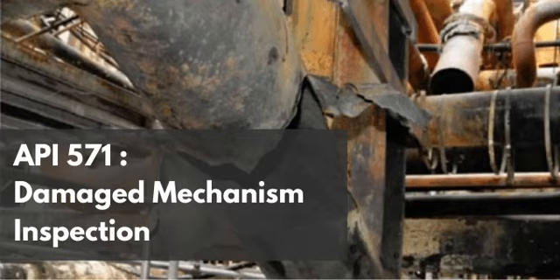Explain that. API 571 makes a definitive, uncompromising statement here. This damage mechanism is exceptionally difficult to find prior to the actual failure of the equipment. It doesn't show up as uniform wall thinning or anything? No, there is absolutely zero metal loss associated with 885 embrittlement. None. Zero. Literally zero. I mean, think about it.